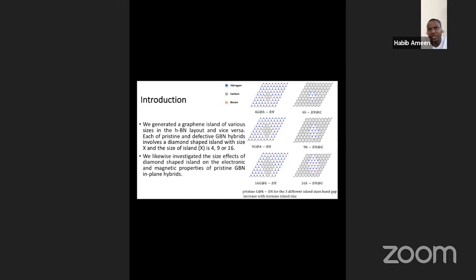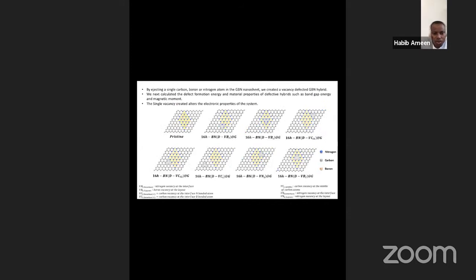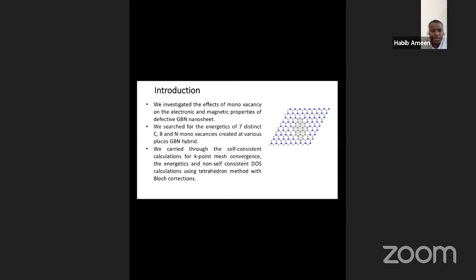So we want to find out how we can tune, especially the band gap of this amazing material. Okay. We also find out how vacancies affect this structure. We remove one or more atoms, whether it is boron or nitrogen, run the calculation, and see how the properties of this material change in terms of the band structure and the electronic properties. Okay, the effect of vacancy: remove one of the atoms, whether it is boron or nitrogen. We also carry out all the self-consistent calculations for the K-point mesh and all the convergence.